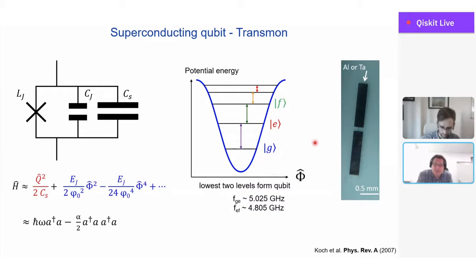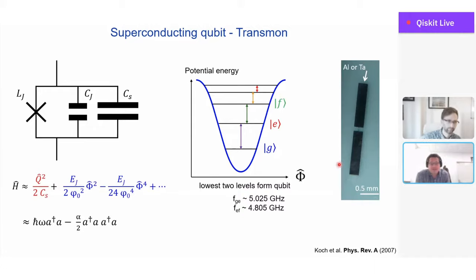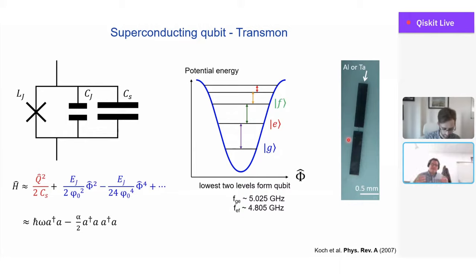In my laboratory where we build what are called 3D circuits, our transmons tend to look like two giant rectangles forming the capacitance, with a tiny nanoscale Josephson junction right in the middle. We make them these days in aluminum or, in my laboratory, mostly tantalum for the big features, with only the small features made out of aluminum. That's how you create a qubit — an example of how we take a harmonic oscillator and infect it with nonlinearity to control it.